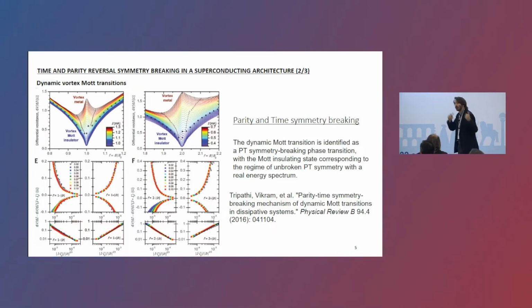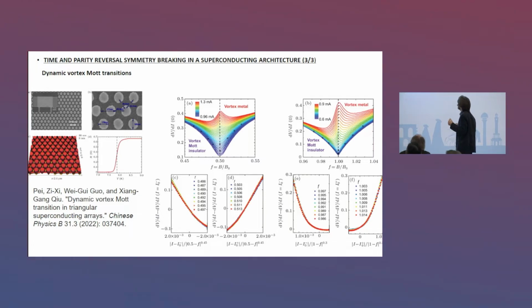Then you can move the system from a non-equilibrium state, the vortex Mott insulator, to another non-equilibrium state, which is the vortex metal, or a responsive metallic state of the vortex lattice. You can do the scaling, and what you discover is that you are in the liquid-gas transition universality class, or in the Mott class at finite temperature. You can also describe the dynamic Mott transition as a parity-time symmetry breaking phase transition, with the Mott insulating state corresponding to a regime of unbroken PT symmetry with a real energy spectrum. This experiment has also been reproduced in a different configuration, a triangular superconducting island proximity array, and the results are similar. So the dynamic vortex Mott transition has been observed in multiple configurations.